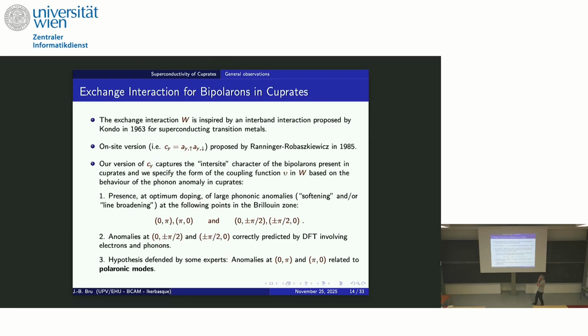And there is a property about phonon excitation. So this is related with phonon excitation. And there are two phonon anomalies in this, a phonon anomaly for two kinds of quasi-momenta. This one, 0 pi or pi 0, which was my example here, and also 0 pi over 2, plus or minus. The origins of these anomalies are different, and this one can be explained by density functional theory without any problem, whereas this one cannot be explained by density functional theory. What is an anomaly?